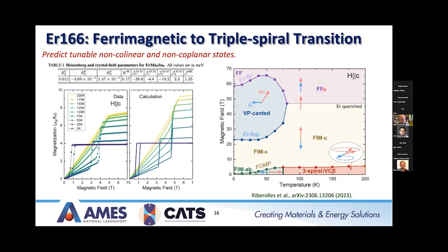And then, this phase diagram on the right here is the same one Joanna showed before. Rob predicted this based on his mean field theory. So interestingly, as you apply a field, you get these various non-collinear, non-coplanar states, which may lead to some interesting topological consequences by picking up this non-zero Berry curvature.